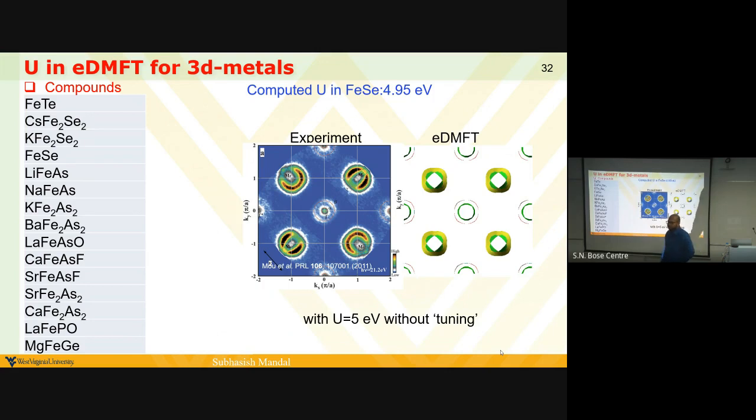That is true. Now, when I come back to the basic question of U, what is the actual U? That's the question: the actual U in which method? In the DFT method, there's a different U. Even in DFT, which basis you are working in, which method you apply it with. It's a real space concept. In DFT, you don't actually have real space. You have only electron density. So you have to know on which particular site you are going to apply it.